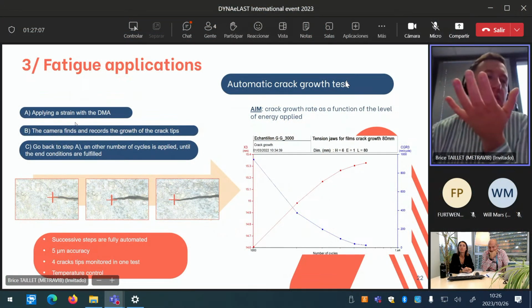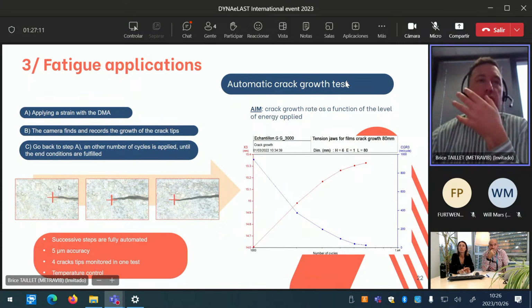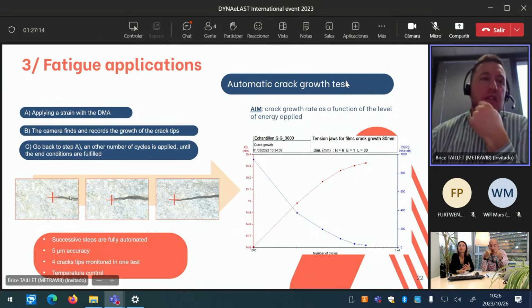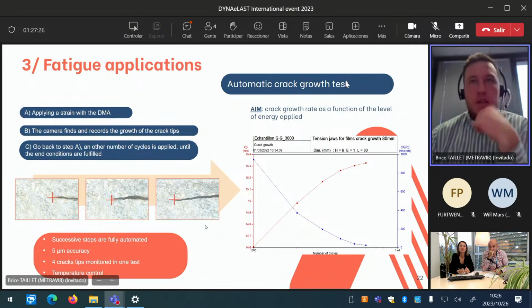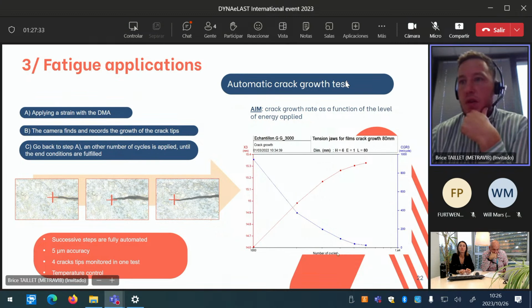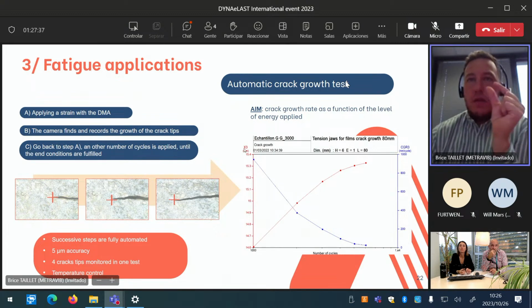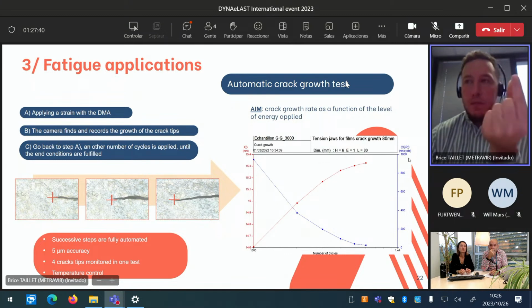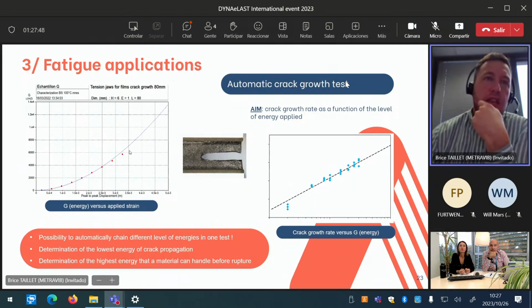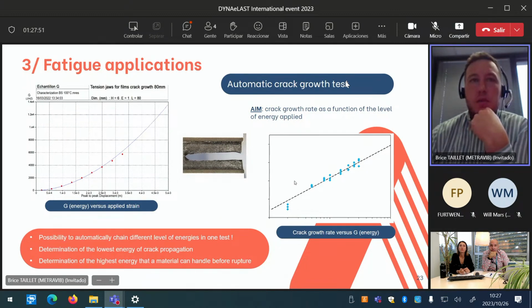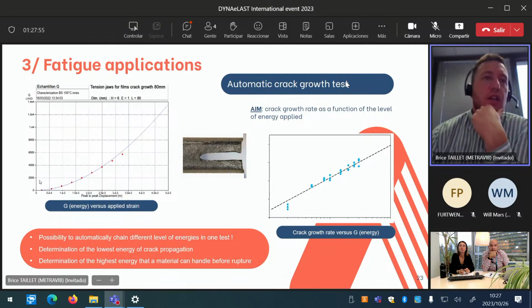So the aim is quite simple. We apply a strain, a dynamic strain with the DMA. We can combine it with a static strain as well. We start to propagate the cracks, and the camera is able to find and to record the growth of the crack tips, okay, automatically. The aim is to get the evolution of the crack growth, that is to say the red curve as a function of number of cycles, and with the length of the cracks, we are able to compute, to calculate the speed of the cracks, the crack growth rate in nanometer per cycle. Okay, and we are able to get this kind of diagram, and this one as well, that is to say the level of energy as a function of dynamic displacement. This is peak to peak in meter.